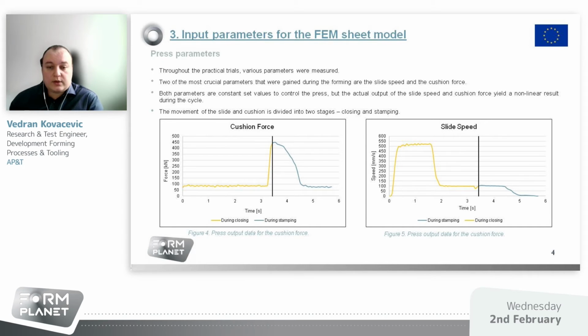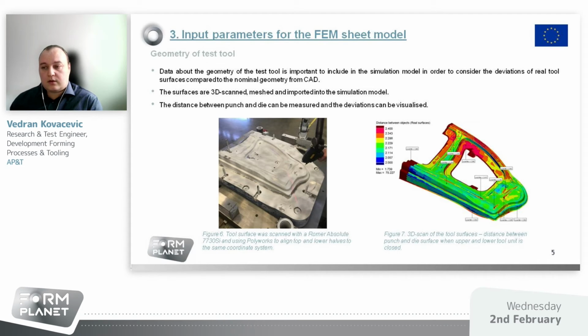Throughout the practical trials, we measured various parameters, but 2 of the most influential ones are the slide speed and the cushion force from the press. Both parameters are constant set values to control the press, but the actual output yields a non-linear result. After forming, the tool's surfaces were 3D scanned in order to visualize the difference between the nominal CAD geometry and the actual tool geometry. The scanned tool surfaces were then meshed and imported into the simulation software PAMSTAMP.